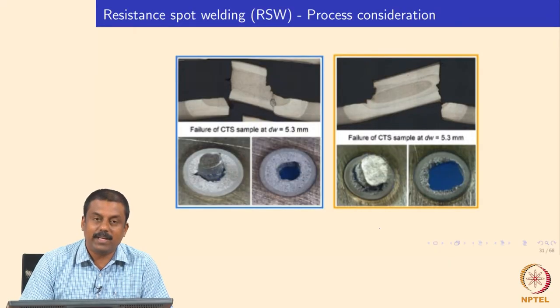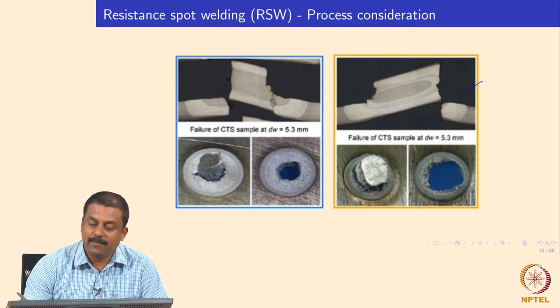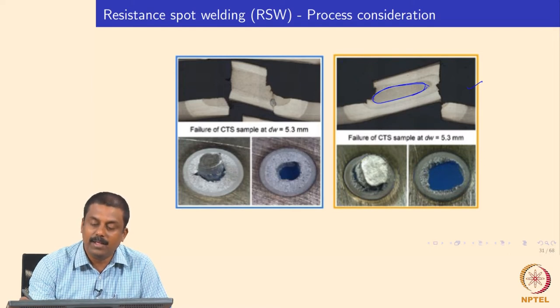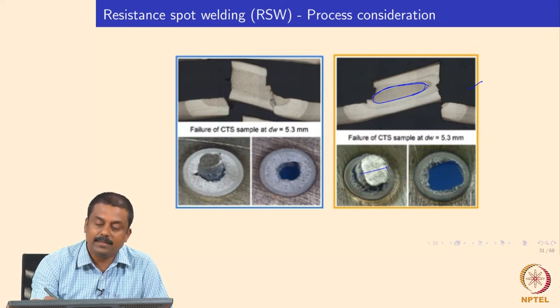We will look in detail at the plug ratio explained in the previous slide. There are two images shown here — a cross-sectional image and a top view after the cross tension test. If you have a well-formed weld nugget and the failure mode leaves the weld nugget diameter intact, that means the plug size is the same as the weld nugget diameter. This is the most acceptable failure mode because failure has happened not in the weld zone but at the heat-affected zone.